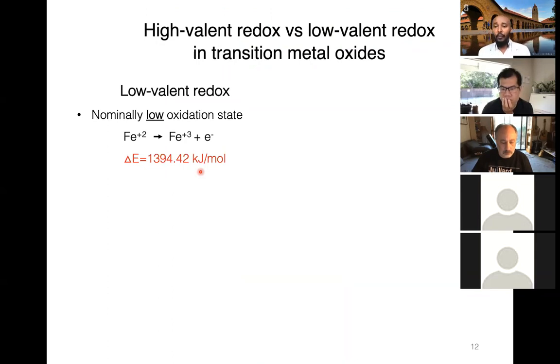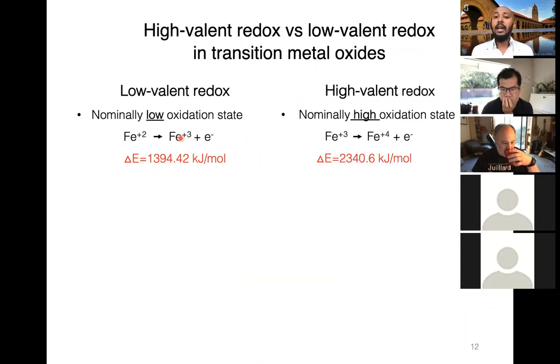In order to define high-valent redox, I would like to draw a parallel with what we call low-valent redox. What we call low-valent redox is a redox process that nominally involves a low valence state of a given element. For example, iron plus 2 to iron plus 3, which is the low valence state of iron, we call this process a low-valent redox. However, in high-valent redox, we nominally involve a higher valence state. For example, iron plus 3 to 4 oxidation, as opposed to 2 to 3 oxidation, is called a high-valent redox process because we have a high valence state of a given material.